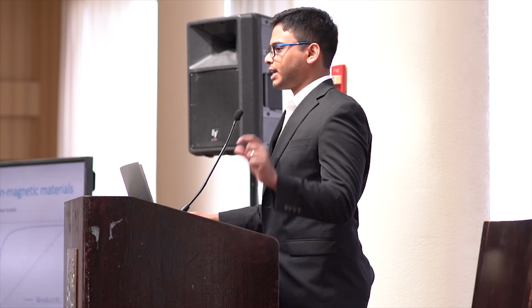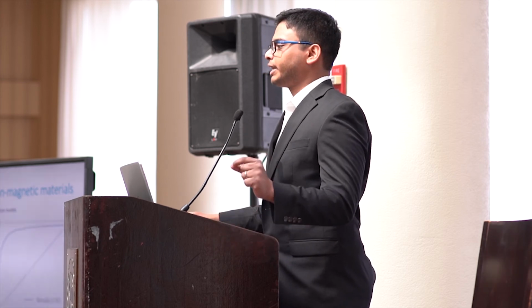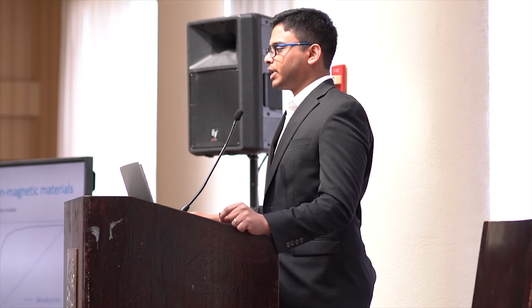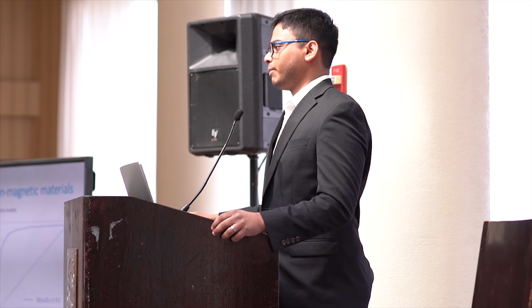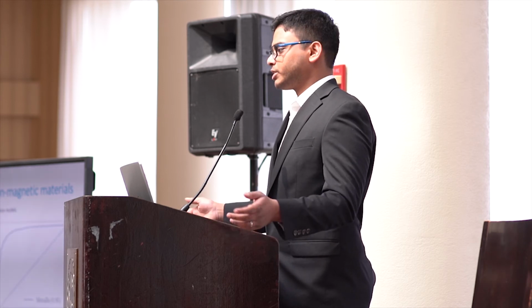So I use this model for something called classification of materials, such as whether a material is metallic or non-metallic, like has a band gap or not, and whether a material is magnetic or non-magnetic. So using the 1,557 descriptors for 25,000 materials, we found that we really get a 96% accurate classification model for metal and magnetic material. So if you give me a material, silicon, my machine learning model will predict whether it's magnetic or not. I think that's cool, without using any physics.